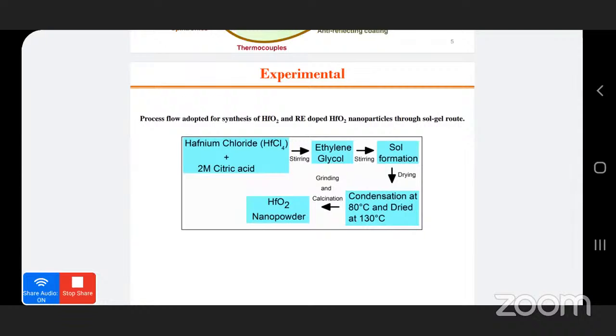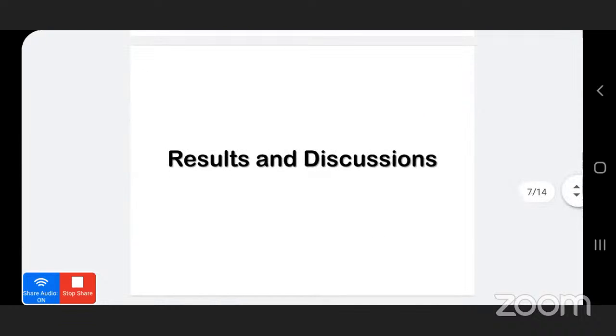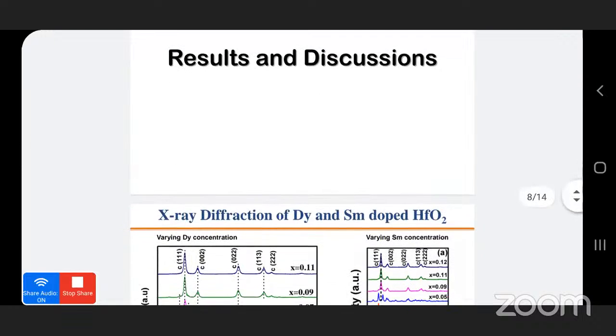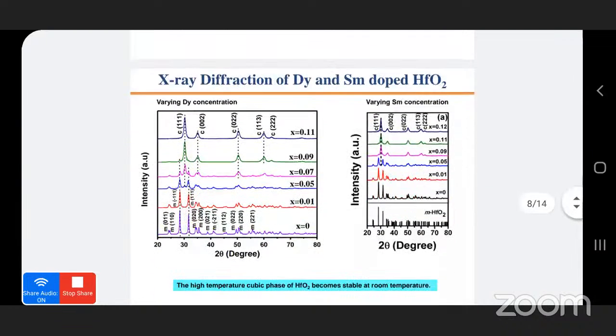So we have chosen 900 degrees Celsius as the calcination temperature for all the samples synthesized with different concentrations of dysprosium and samarium. The idea of incorporating these trivalent rare earths, such as dysprosium and samarium, is to obtain the cubic phase. In the introduction I mentioned that the higher symmetry phases of hafnia, the tetragonal and the cubic phase, exhibit a high K value, which is very useful for MOSFET applications. We all know that SiO2, silicon oxide, shows a higher leakage current as we reduce the thickness. So we need to opt for alternate materials having high K values.